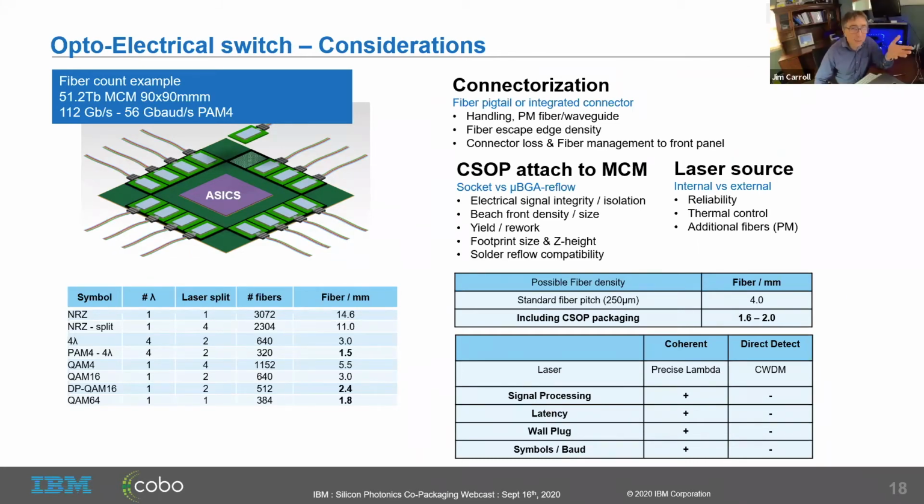Excellent. Do you have already any data supporting reflow compatibility for the V-groove based fiber attached solutions, or is there any possibility that you'll find a suitable epoxy? Yes, we have demonstrated reflowable. We even demonstrated reflowability on the full flip chip module, so the complete assembly, not only the fiber attach, but with the PIC inside the package with the flip chip photonic chip, was reflow compatible. The main problem is the ferrule. So currently our solution is to have longer pigtails and protect the ferrule from the heat, because it can support some heat, but not too much.